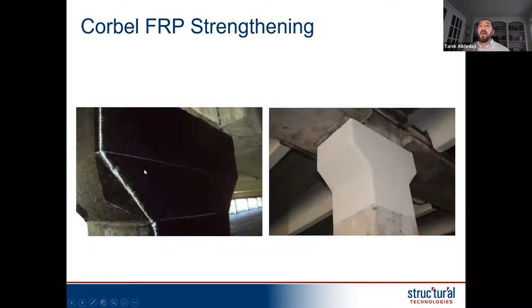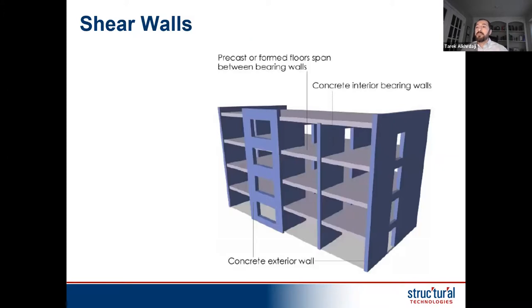And then once it's wrapped completely, now the nice thing about composite is they're watertight. So when you wrap it, not only does it provide confining force that adds capacity, but it's also sealing the surface to some degree. So water is not going to get in from the side at least. As long as the waterproofing on the top side is done correctly and there's no water coming in through the joints, then this element will have additional or extended protection against corrosion.